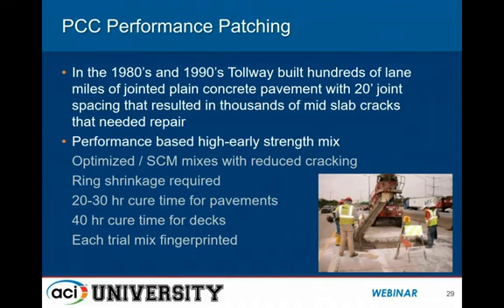So moving on to Portland cement patching, this is some work, again, that was done in conjunction with the Illinois Tollway, and they were trying to address the cracks that were occurring with the prescriptive repairs. And what we ventured into in this case was optimized concrete mixtures that, again, utilize the ring shrinkage test so that we can prevent the cementitious content from becoming excessive. Trying to get the strength that we need, but not over-design significantly for that early strength.